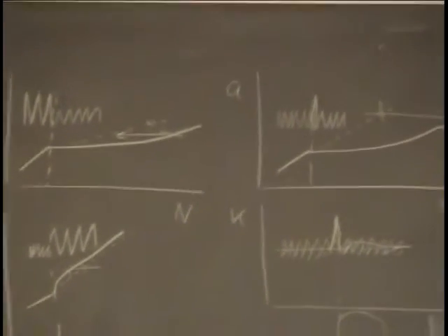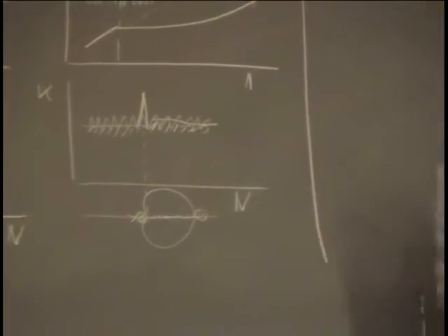Now, finally, any questions on crack closure here? I mean, the thing is a bit more complex. We induce negative residual stresses and so on and so forth. We did also high-resolution X-ray measurements to determine the local residual stresses. But the picture that we gave is the same as with the level of the plastic zone here.